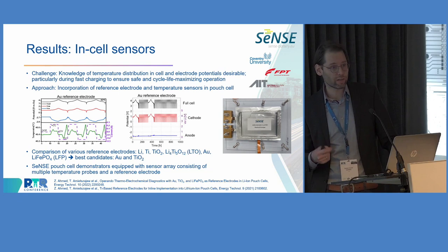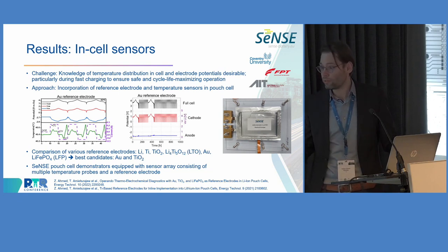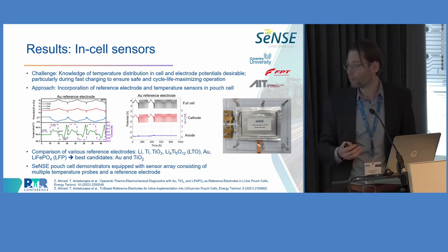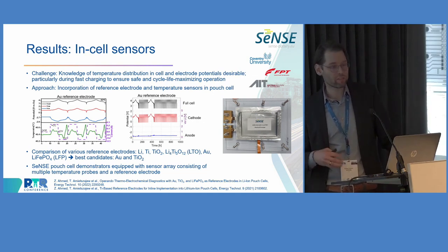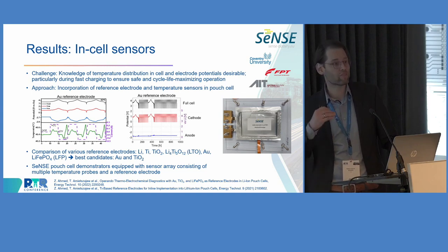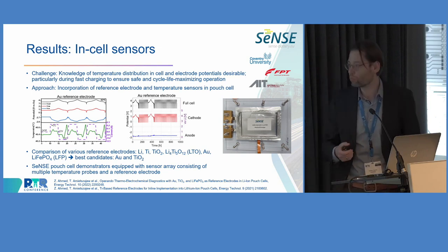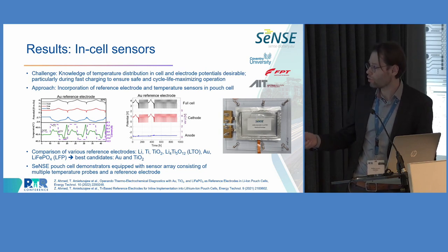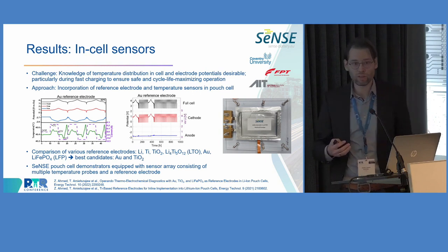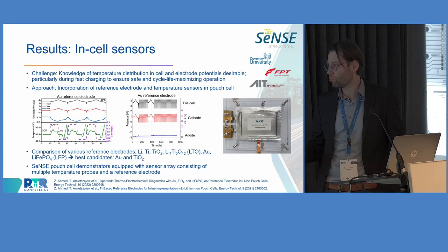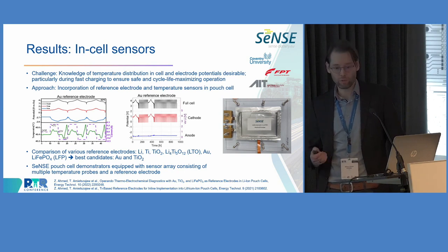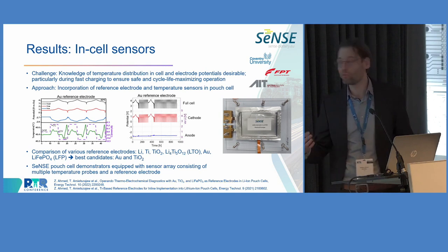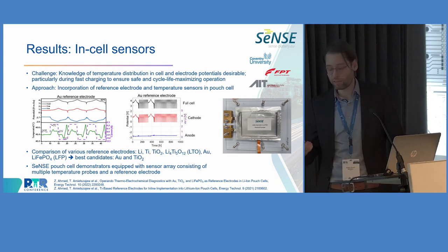If you have a reference electrode inside, you can monitor the electrode potentials individually for the anode and the cathode. It turned out that both gold and titanium dioxide are quite promising candidates, because these reference electrode materials offer long-term stability in the cell and also don't require a pre-lithiation step that is needed for some other reference electrode materials. As I mentioned before, the first pouch cell demonstrator that we produced last year incorporates temperature probes and also a titanium dioxide based reference electrode. At the moment, we are working on fast charging algorithms that make use of these sensor data.